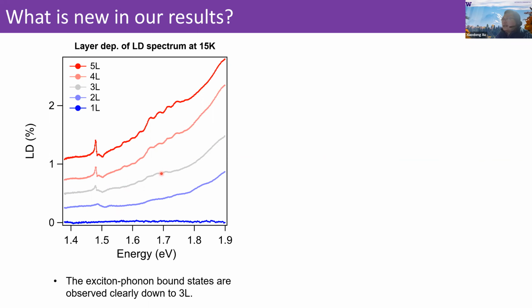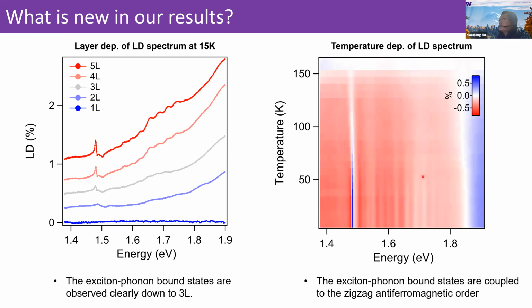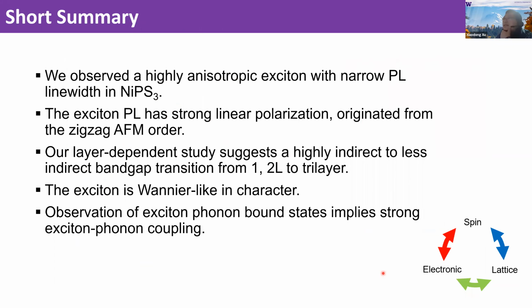crystals. And the other new thing is that here I show you the temperature dependence of these LD spectra. You can see these wiggles, the fringes, represent the exciton phonon bound states, and they have a strong temperature dependence and vanish above the Néel temperature. So what it means is these exciton phonon bound states are also coupled to the zigzag antiferromagnetic order. And the coupling between these exciton phonon bound states and magnetic order has also not been observed in the past. So this is new.